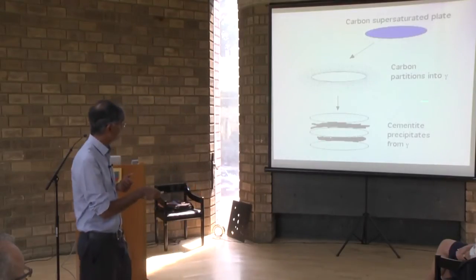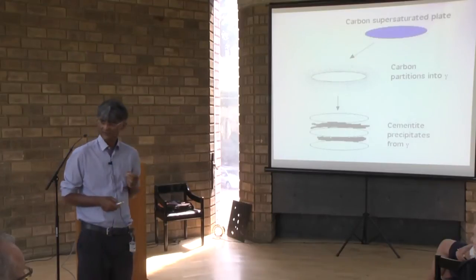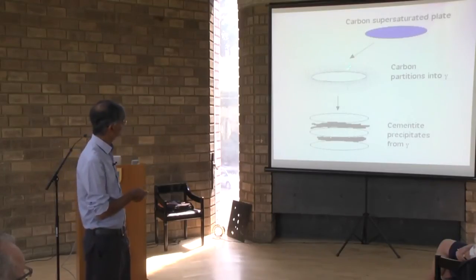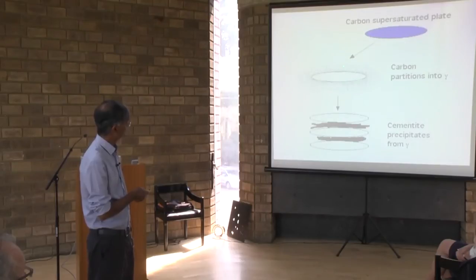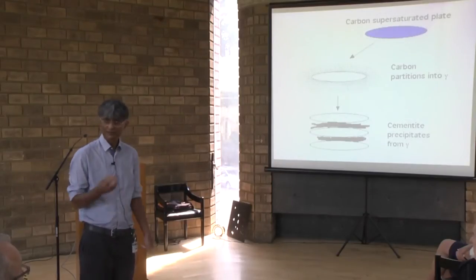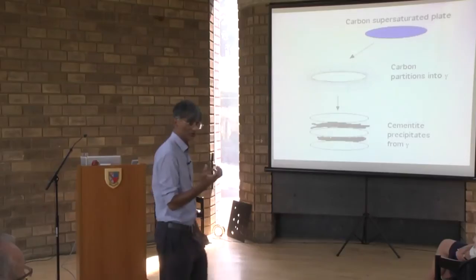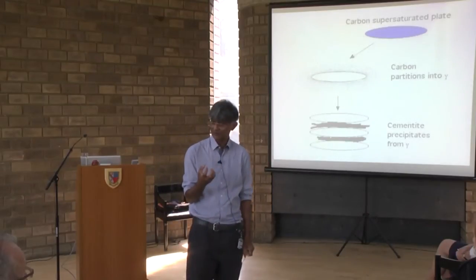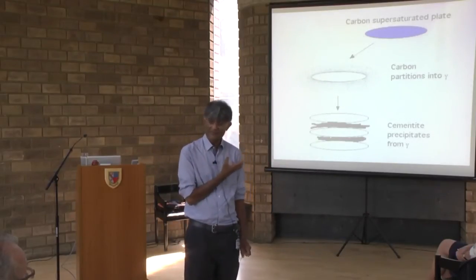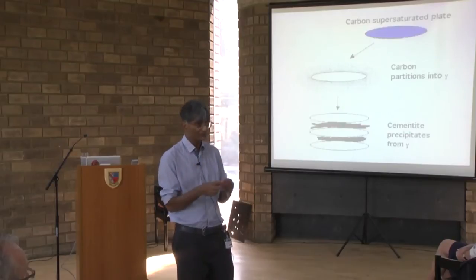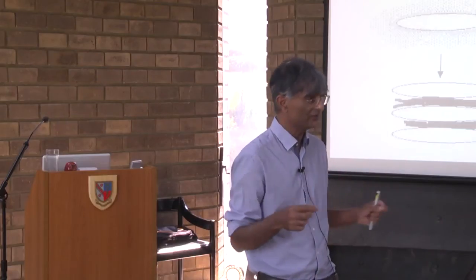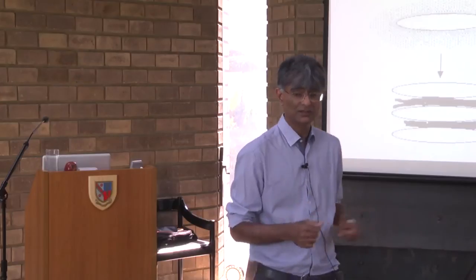We can stop this reaction here by adding certain elements. So by doing that, we end up with a mixture of the parent phase and the product phase. And the parent phase is very good for absorbing energy and for providing work hardening. So this is basically an ideal structure. We are getting fine plates, we are retaining some of the parent phase, adding work hardening capacity.